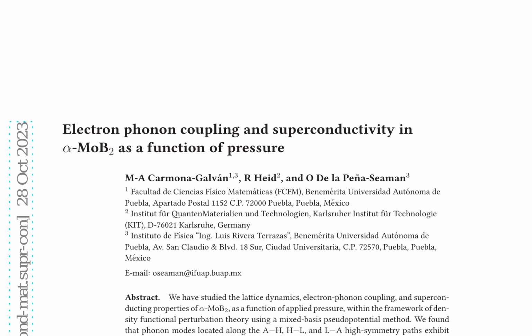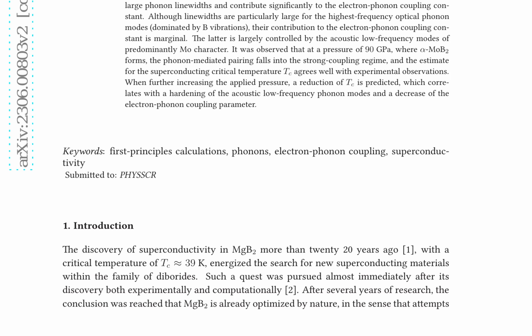At a pressure of 90 gigapascals, where alpha MoB2 forms, the phonon-mediated pairing enters the strong coupling regime, and the estimated superconducting critical temperature Tc aligns with experimental observations. Further increasing the applied pressure leads to a reduction of Tc, correlated with a hardening of the acoustic low-frequency phonon modes and a decrease of the electron-phonon coupling parameter.